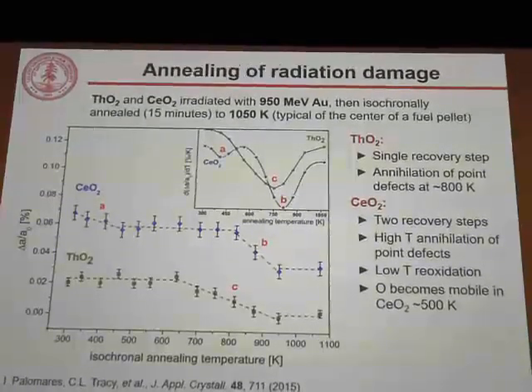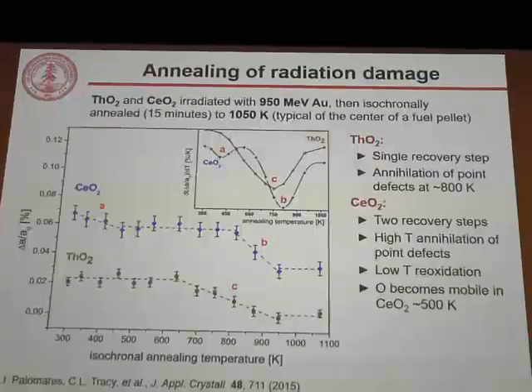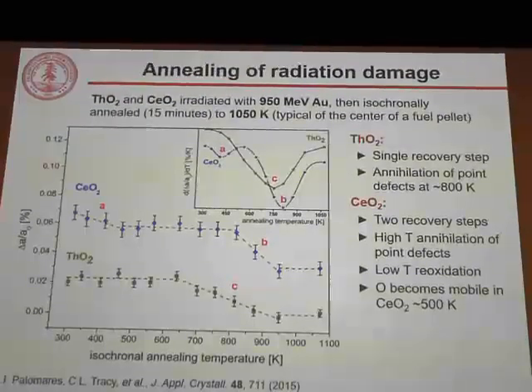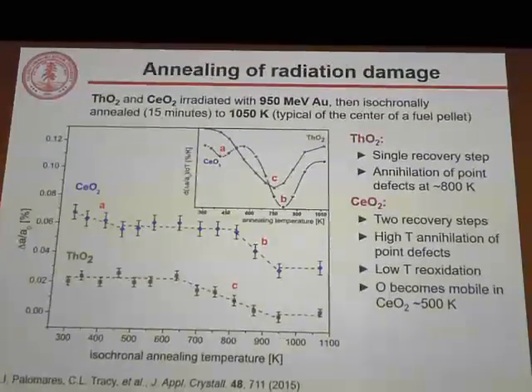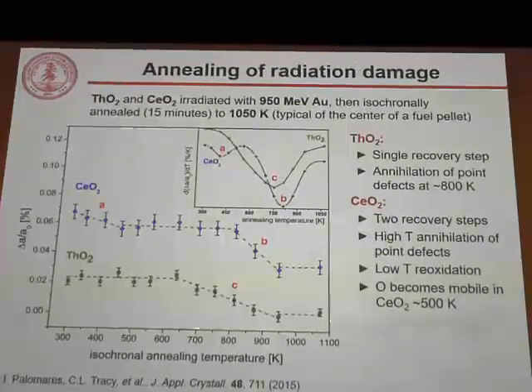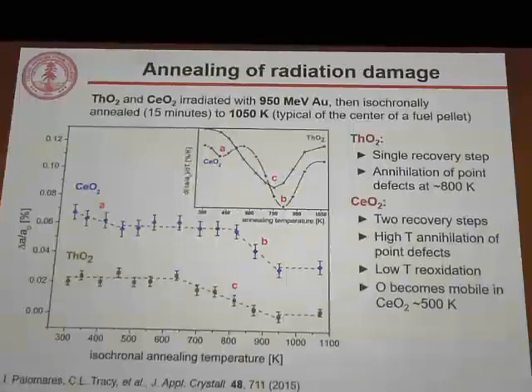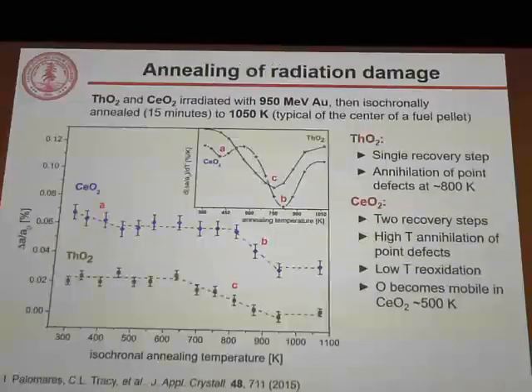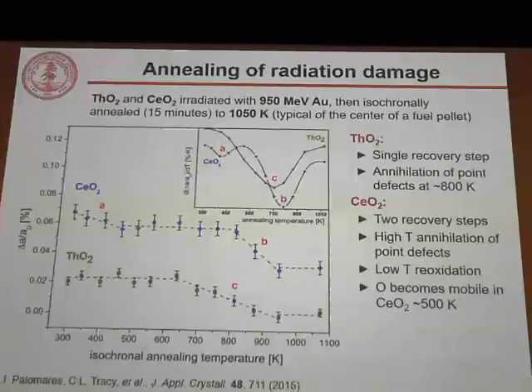And again, comparing cerium dioxide and thorium dioxide, we see very different behavior. Thorium dioxide, as we might expect, has a single recovery step associated with the annihilation of point defects at relatively high temperature, about 800 Kelvin. Cerium dioxide has the same high temperature point defect annihilation step, but also at lower temperatures, a different low temperature recovery step, which is associated with reoxidation of reduced cerium.